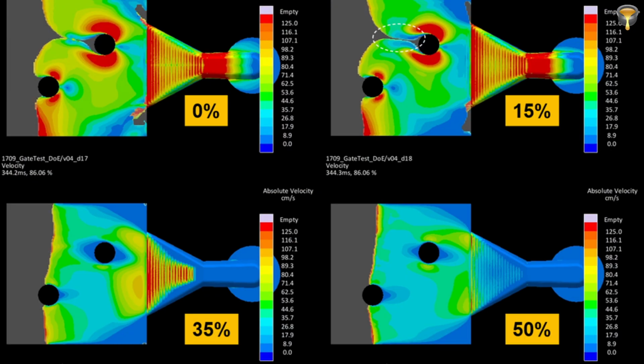And you have a very nice picture of what you just said, where you see the different solid fractions in simulation, where you have a couple of cores going into the cavity. And you can actually see that at 35%, the magic starts. Exactly. And there's also what isn't shown in that picture. I call it the dead zone. That's between 20 and 30%, where you have that constant switch-over between laminar fill and turbulent fill, and that is where you 100% produce scrap parts if you slide into that with your process. The zone of death, you hear that?